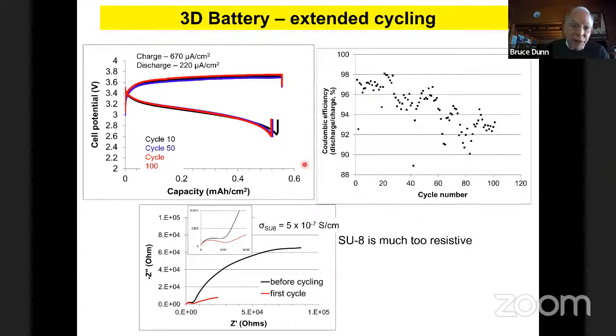And what we found is that, yes, you can get pretty good cyclability out of these systems, but only if you cut back on the capacity. And again, you don't really want to cut back on the capacity. So you have to really compromise in that regard. The other part that happens is that as you cycle this, you can get cycles out of it, but the Coulombic efficiency drops as well. And so that's another problem.